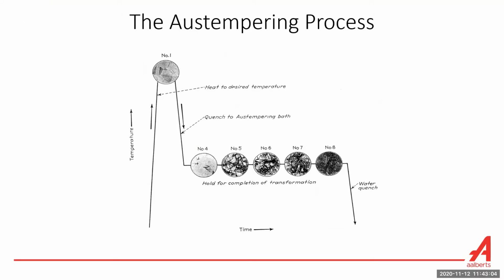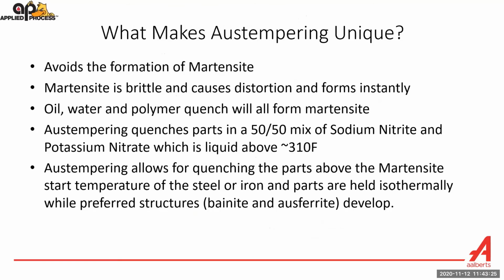So again, we elevate the component to about 1600 degrees Fahrenheit, which would be typical. We quench it, but then we have to hold it while the microstructure develops over time. That's a little bit different than oil quenching or water quenching, which is you quench it, you take it out of the quench tank, you temper it, and you're done. So this is a time-dependent process. So what makes austempering unique?